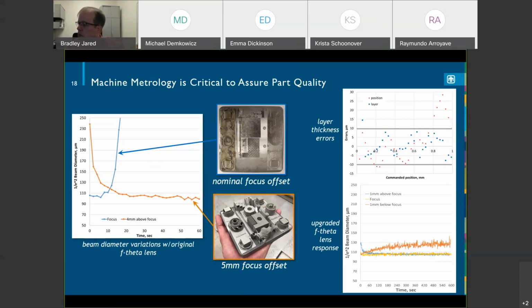So this is an area where we were just measuring basically the motion of the stages, right? We see quite a bit of variability here, which is sort of in the range of what we think would be acceptable, and it seems to work quite well. But this is an area where we actually need to do a little more work. But this is something that you have to characterize. The bottom right is actually, so we did this work with the thermal lensing problem. We actually upgraded our lens with the vendor, and this all went away. So this created a bunch of challenges. We've resolved those now, and so now we have a machine that's very robust. We're printing samples daily with a lot of reliability and trust in what we're getting off the machine.